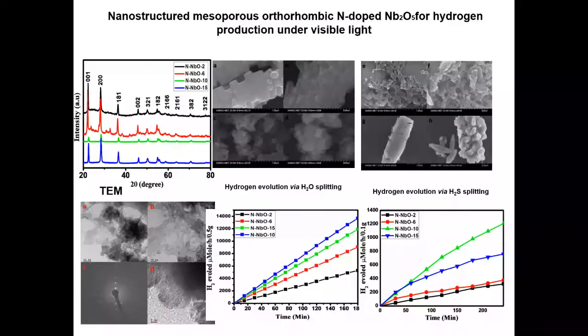This is the catalyst we use, like nitrogen-doped Nb2O5. Nb2O5 absorbs in the UV region, and when you dope with nitrogen, it moves to the visible region. Means the band gap is around 2.4 electron volts. Initially it is 3.2 electron volts. This is the structure. When you dope with nitrogen, the Nb2O5 becomes a little porous, and because of this porosity as well as nitrogen doping, maximum sunlight absorption takes place, and maximum electron holes are generated.